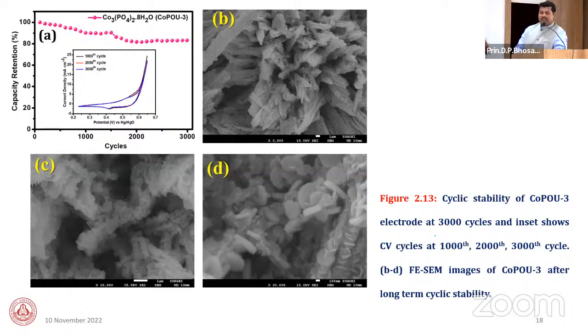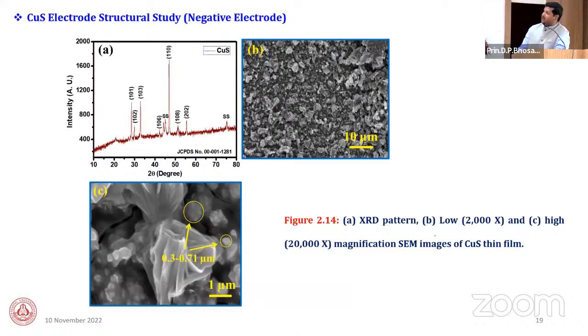Then I tested the cyclic stability of this best electrode in CV study for 3000 CV cycles, and it gives 84% capacitance retention. After cyclic stability, you can see the morphology, and it shows no drastic change is observed in the morphology, just nanoparticles are observed on the surface of these plates. It is observed because of the intercalation of the ionic electrolyte on the surface of the electrode.